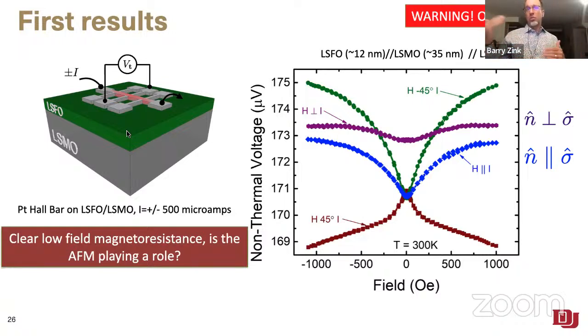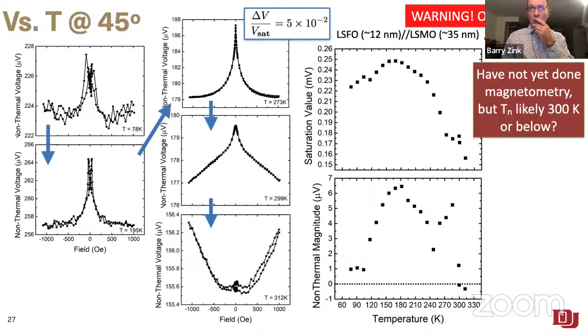The largest raw voltages come out at the 45-degree angles, whether positive or negative, and there's less happening when the magnetization is aligned with the current or perpendicular to the current. From a real bird's-eye view, this maybe aligns with what you might expect from spin Hall magnetoresistance effects. We can look at the temperature dependence. That's basically what this is.